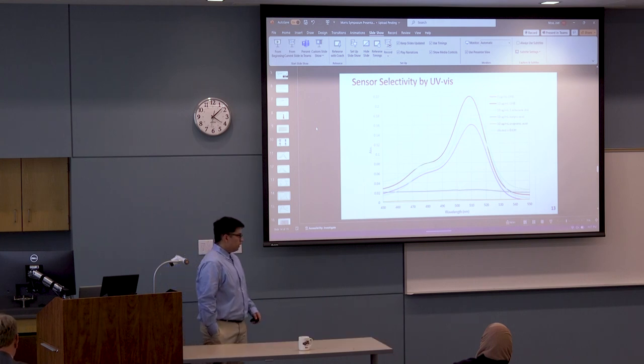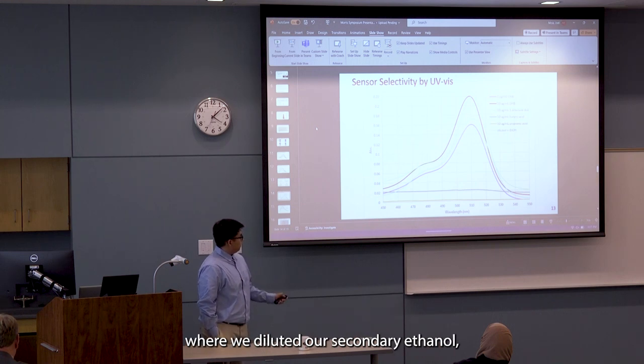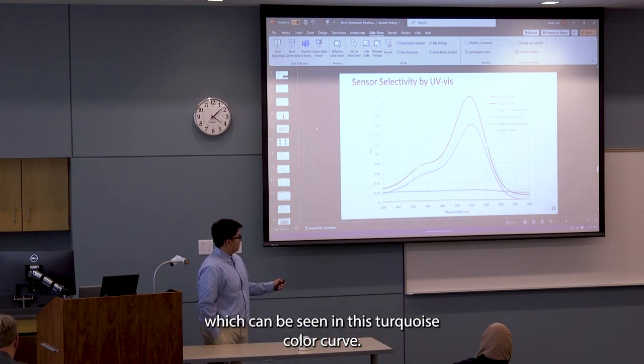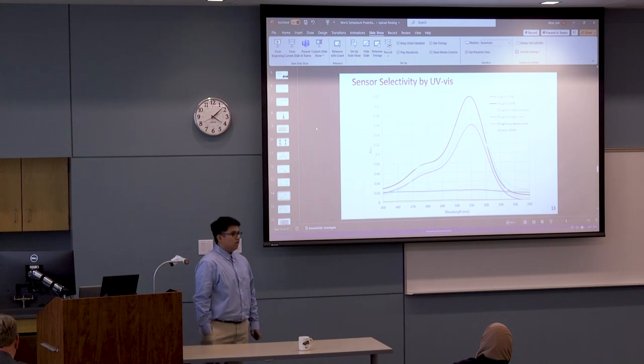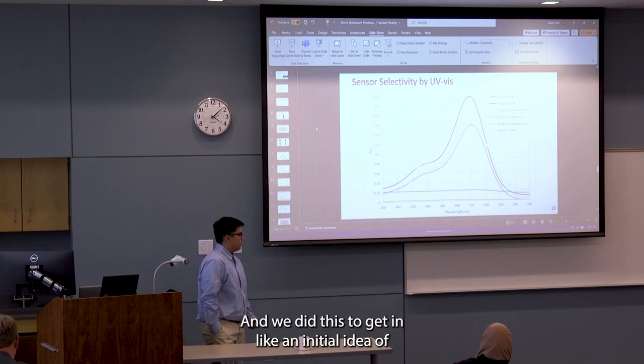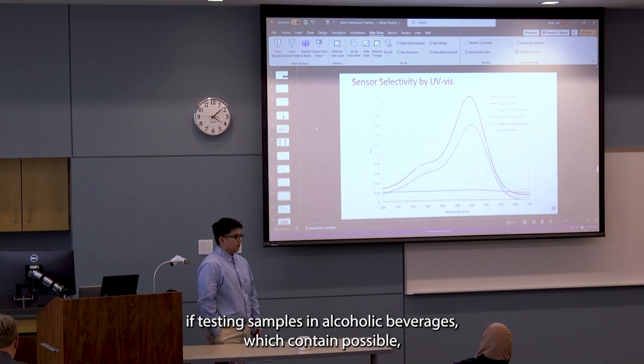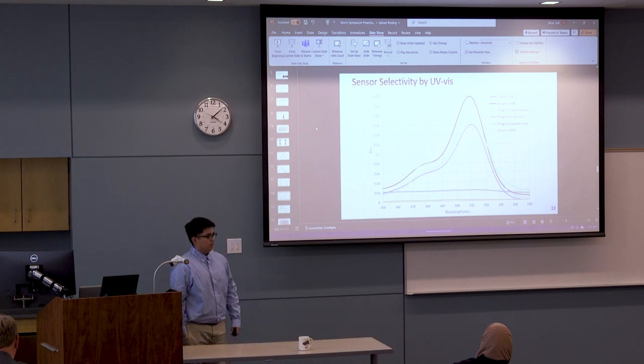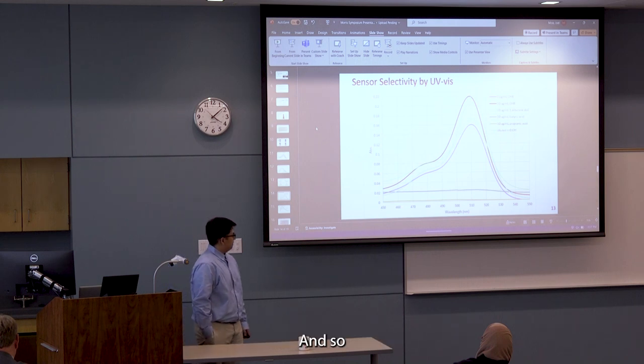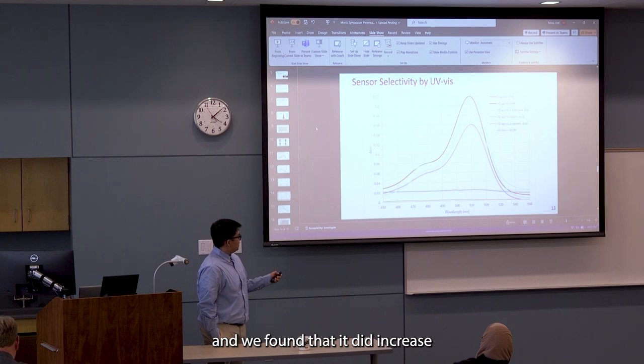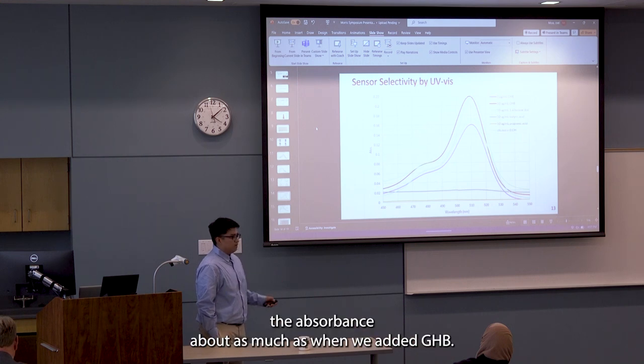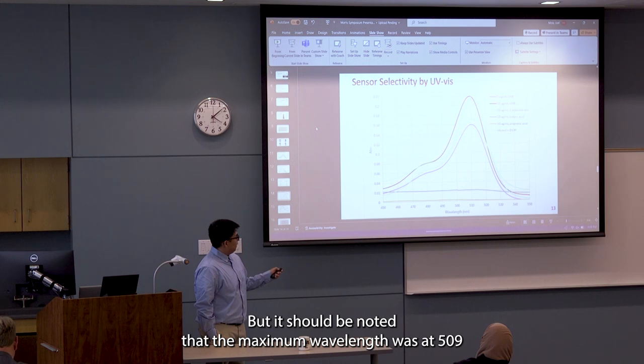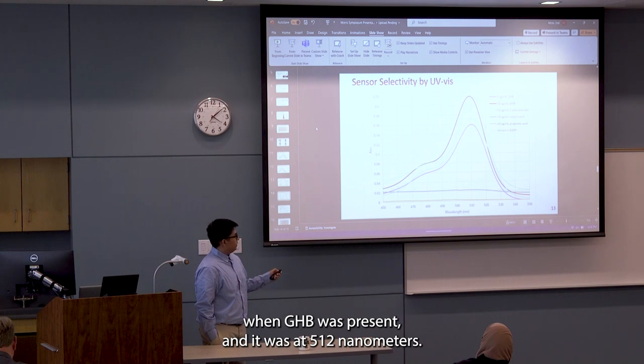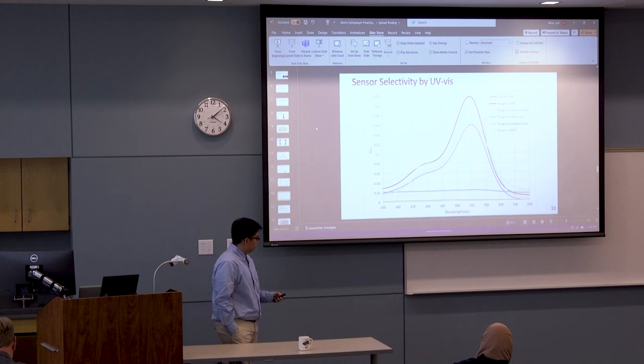We also did one additional test where we diluted our sensor in ethanol, which can be seen in this turquoise color curve. And we did this to get an initial idea of if testing samples in alcoholic beverages which contain ethanol could act as an interfering species itself. And we found that it did increase the absorbance about as much as when we'd added GHB. But it should be noted that the maximum wavelength was at 509 nanometers when GHB was present, and it was at 512 nanometers when we had diluted our sensor in ethanol.